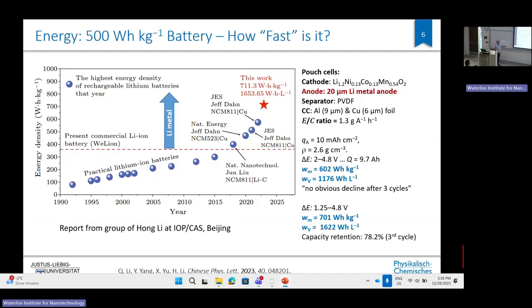I know Hong Li quite well, and I asked him about these very high values for these cells. This is, by the way, a liquid cell with a liquid electrolyte. These cells don't really cycle. So these are designed for demonstrating high energy density and high specific energy, but there is no true kinetic data in this paper. So I would say there's a compromise, and here it's optimized for energy density, but not for cycling. If you were to design it better for cycling, you always lose specific energy. So that's, I think, the drawback of that.